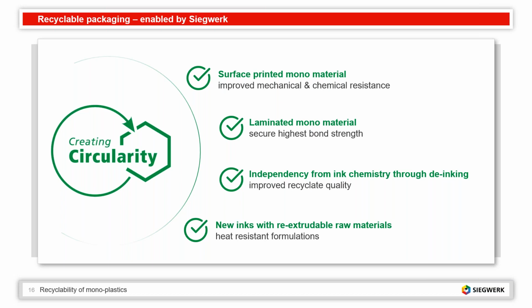So we didn't investigate to this level of detail, but generally speaking, the impact of an overprint varnish on the heat seal window of a given film will be there, but it's a minor impact. If we compare the thickness of the layer of an overprint varnish, it's 1 to 2 micron, and so the heat capacity of this ink layer is not significant compared to absorption of heat in the monoplastic, which then melts and has to seal.